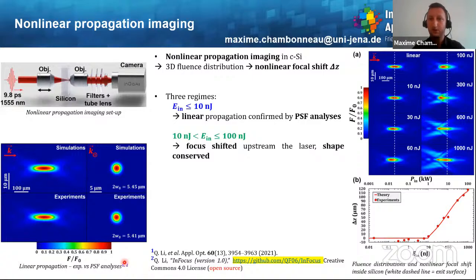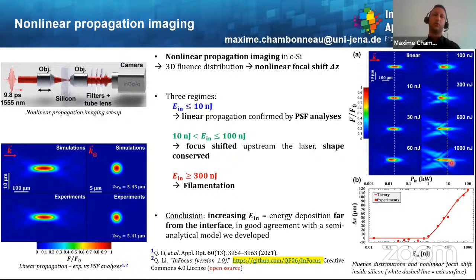Then for intermediate input pulse energies, so back to those data here on the right, between 10 and 100 nanojoules, one can see that the focus becomes unambiguously shifted upstream the laser. However, the overall shape, I would say, is conserved. And then the final regime is when you increase the energy a lot and go to more than 300 nanojoules. Then one can see that we are in the filamentation regime, especially here for 1 microjoule, where you see those focusing and defocusing dynamics. So the conclusion of this is that when you increase the input pulse energy, the energy deposition will be far from the interface, which is in very good agreement with a semi-analytical model that we have developed, which is represented by the solid lines here on this graph.